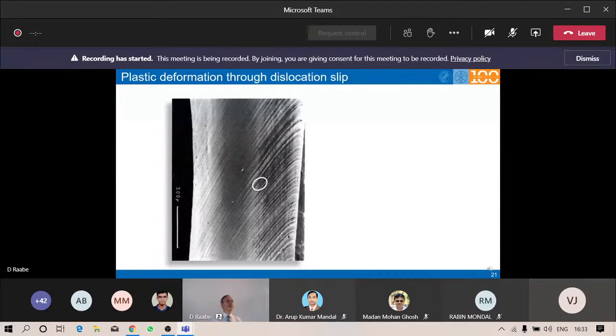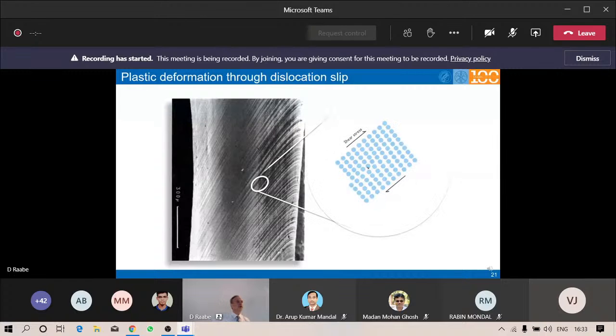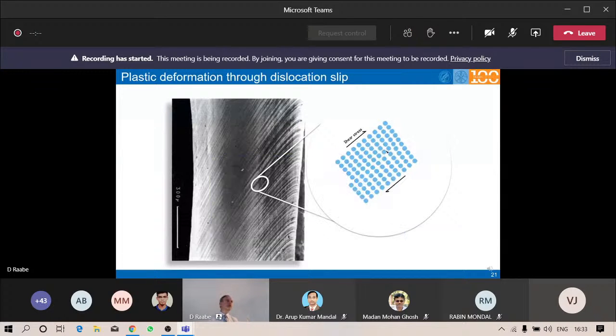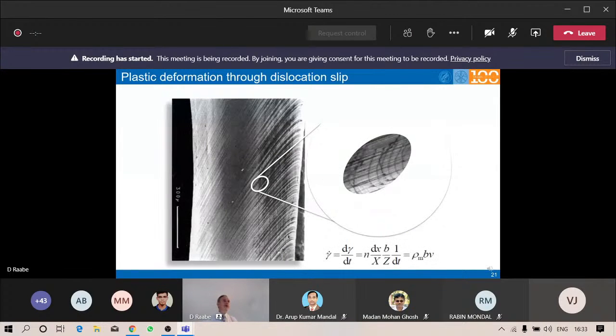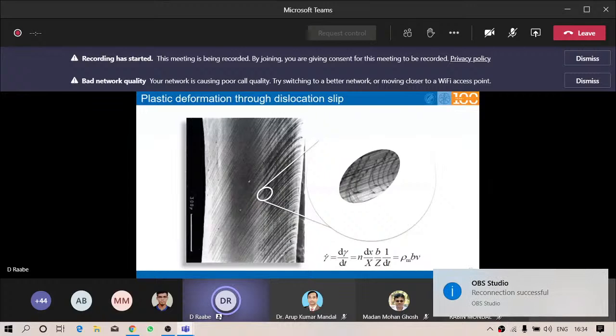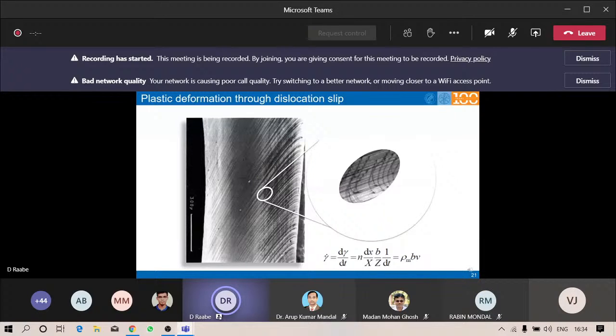Here you see such a nice picture from a textbook with surface steps coming from the glide of dislocations. Of course, the surface steps are much bigger than one Burgers vector because we have a number of dislocations coming from the same source. And then you can use, like plotted here, the well-known Orowan equation, which allows you to calculate the shear rate gamma dot from the activity of these mobile dislocations, their Burgers vector, and their velocity field. So you have a very simple mean field access from Orowan theory, from Kocks-Mecking type of theories, to translate populations of many dislocations into the corresponding kinematic measures that you need.